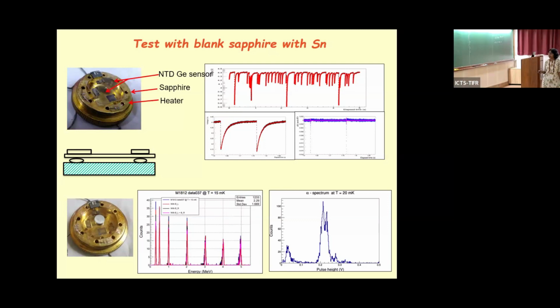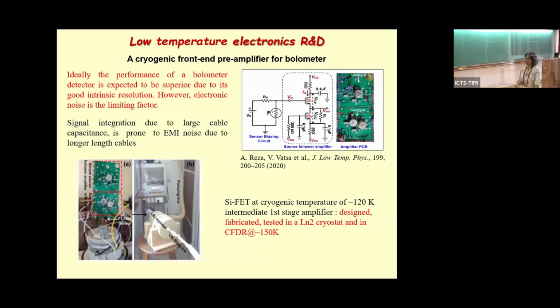We see good linearity and good resolution, but we do not get good resolution yet with the alpha particle source. So it needs improvement. The first limiting factor we found was the noise, and we have gone further to understand it. There are two things you have to do in case of noise. One is that we need to put the preamplifier stage at low temperature, because then the cable capacitance effect gets reduced. So that's being designed.